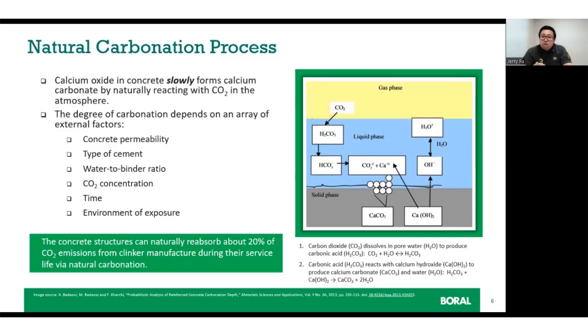During carbonation, CO2 diffuses into the pores of cement-based materials and reacts with hydrate products such as Portlandite and CSH in the presence of this acidified pore solution. The carbonation starts at the surface of the concrete or mortar and slowly moves towards the core of the material. This process is also influenced by a range of factors such as CO2 concentration, hydration product compositions, and exposure time.